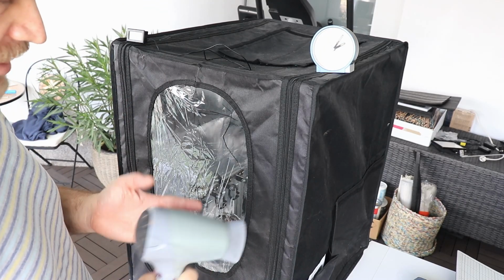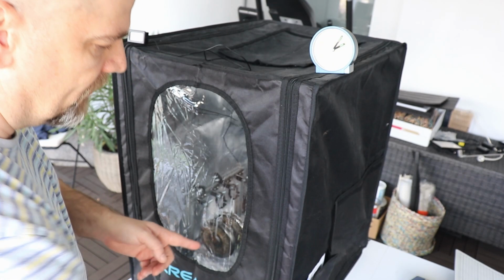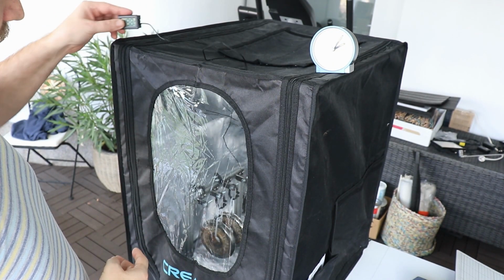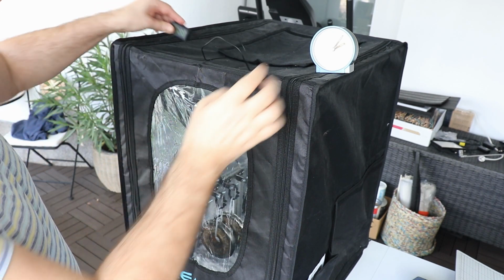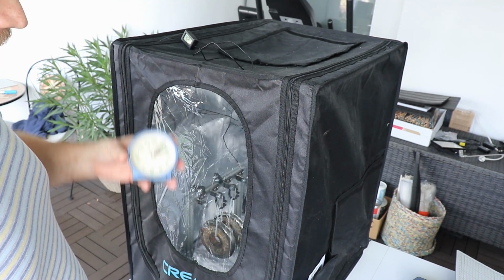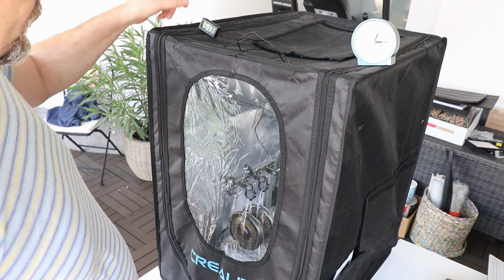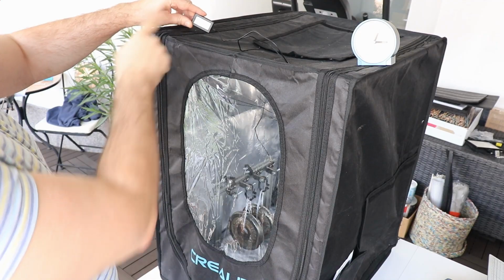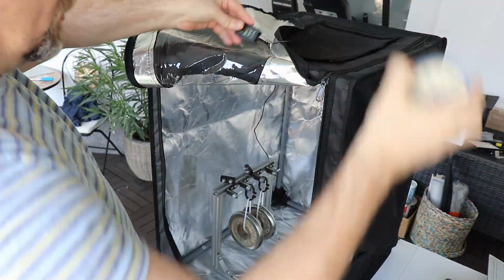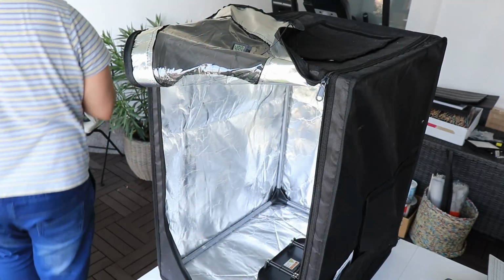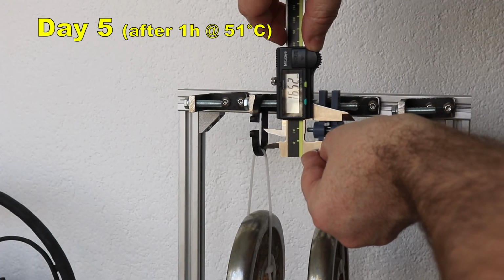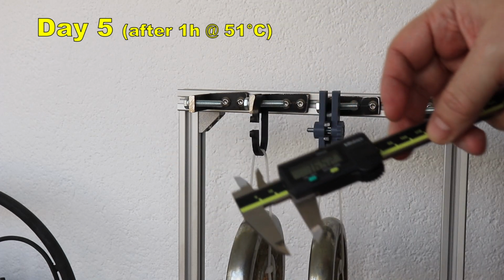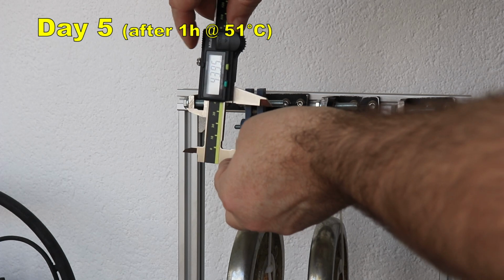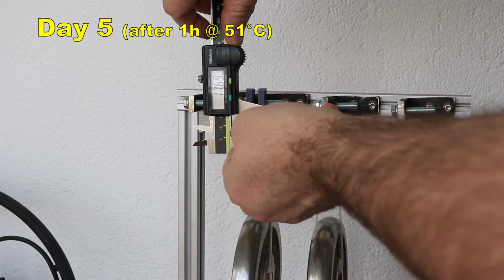I heated up the temperature with this air blower to 50 degrees Celsius, and now I have the filament dryer which will keep this temperature, and currently it is 50 degrees Celsius inside, and I will measure the creeping after 1 hour. And it's time to finish the experiment. The temperature went up to 51 degrees Celsius. ASA 16.52. Almost no changes. ABS Plus 17.69. And this is almost half a millimeter of creep at 51 degrees Celsius in 1 hour.